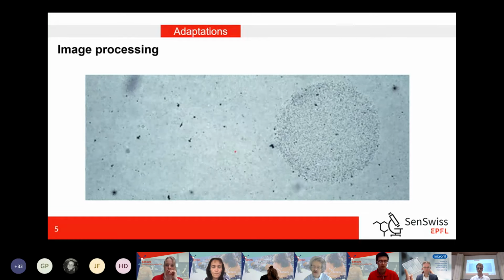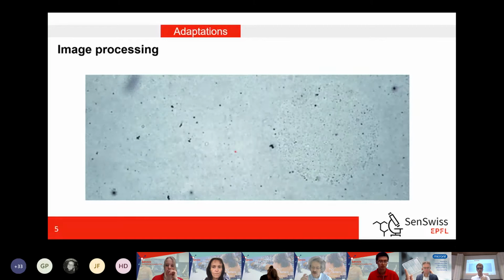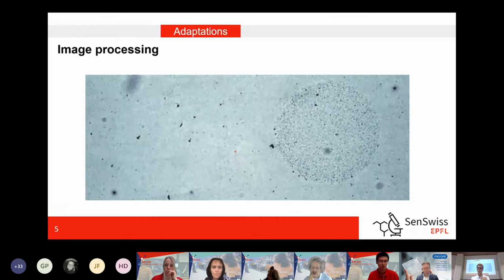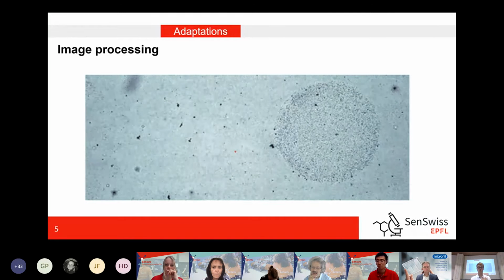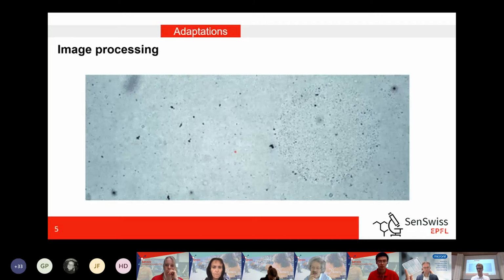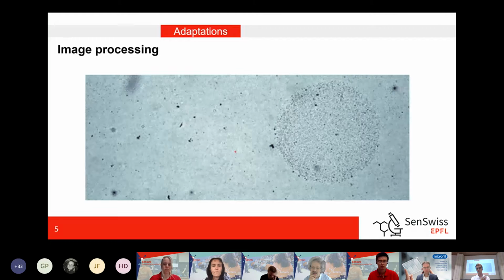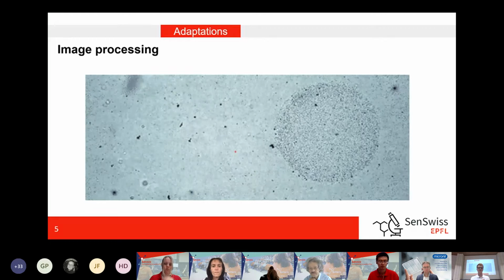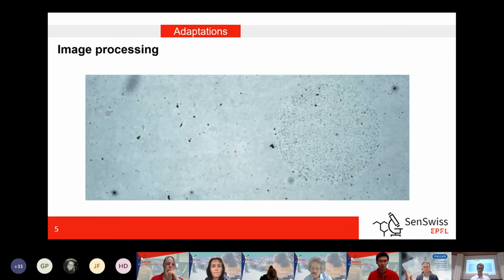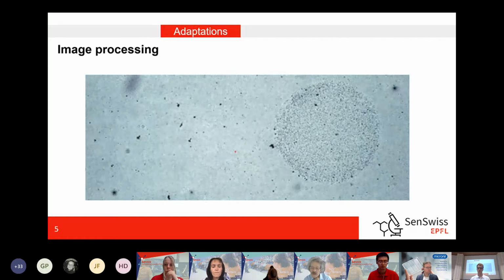Doesn't that limit the accuracy of your measurement when you have a high density of gold nanoparticles on your surface? Then they almost look like clusters, and it becomes very sensitive to your thresholding. Yeah, it's a good question, and we definitely have to verify the gold nanoparticle concentration. You can't go too high, else it's a problem. At the moment, our concentration is 0.26 nanomolar. I know these numbers don't mean a lot, but at the moment it wasn't too big of a problem. The filtering worked quite well, and there's no excessive binding. As long as you mix the nanoparticles well beforehand, there's no problem.